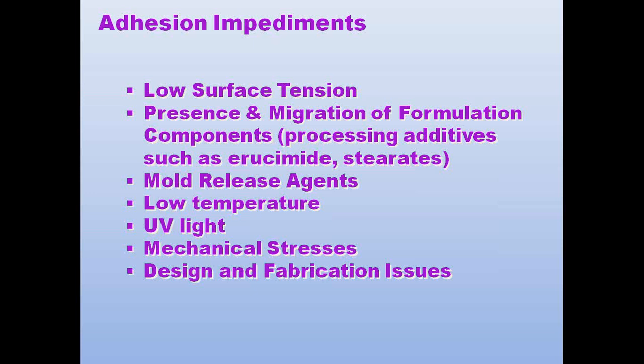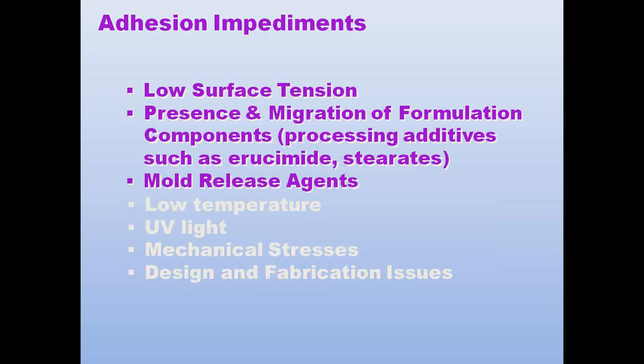A lot of this stress, a lot of these environmental factors and exposures need to be incorporated into the design, form, and function process. So designing and fabricating appropriately will minimize the effect of these stresses on adhesion. But when we boil it all down, it really comes down to the top three: low surface tension, additives, and mold release agents that are the biggest issue with regard to achieving and maintaining long-term adhesion.